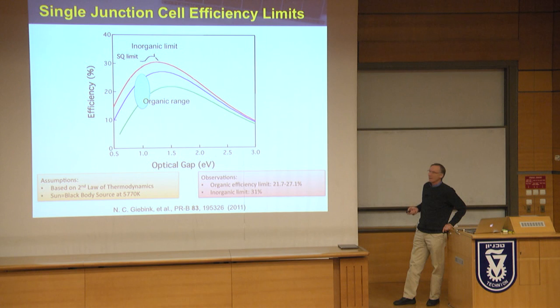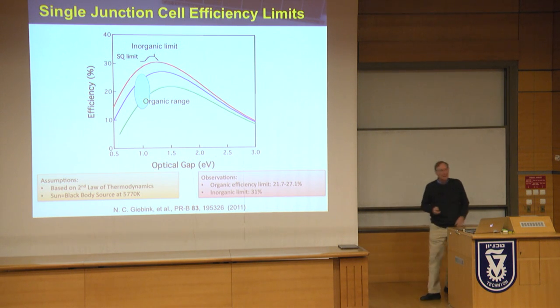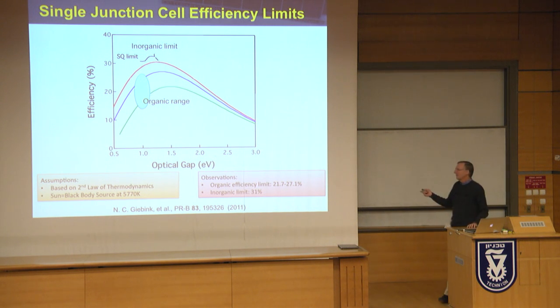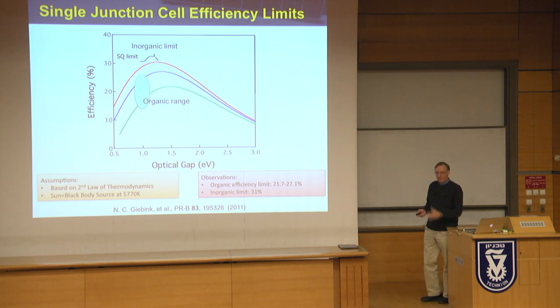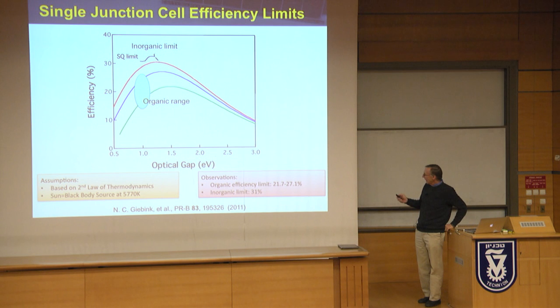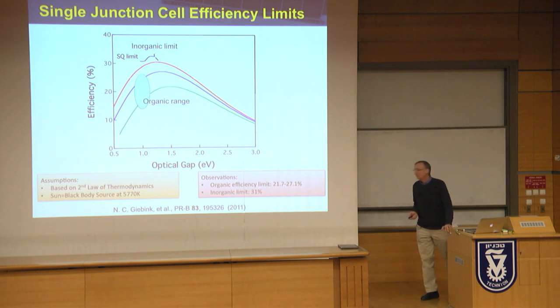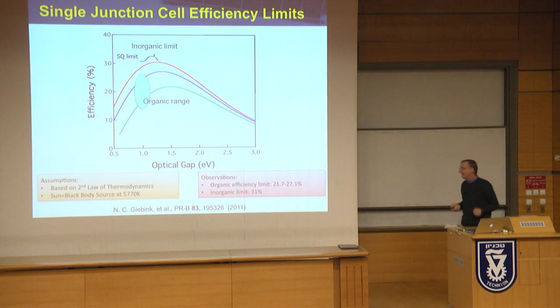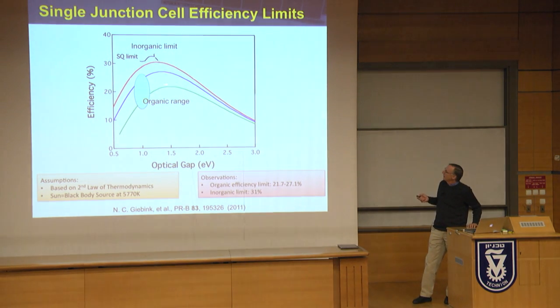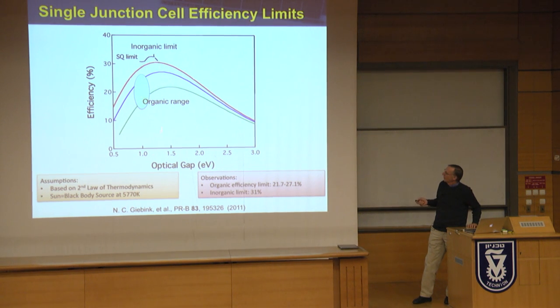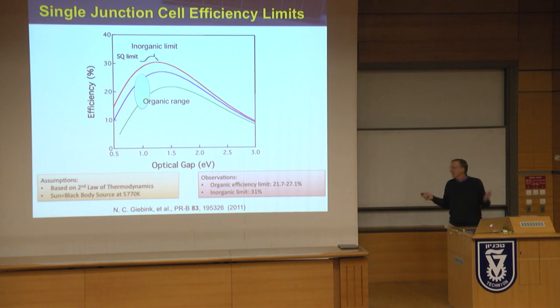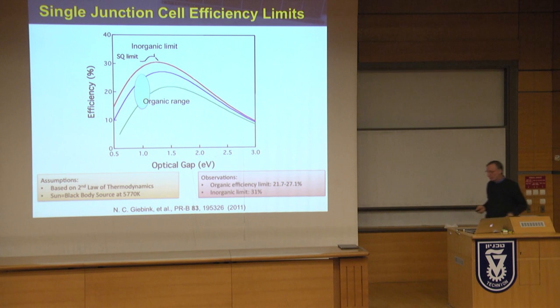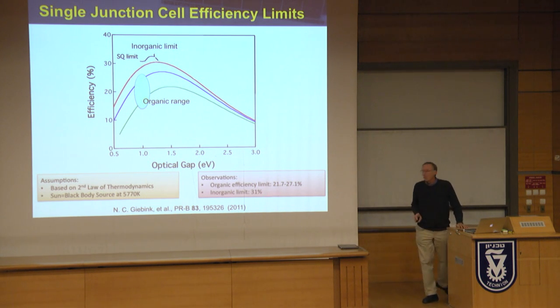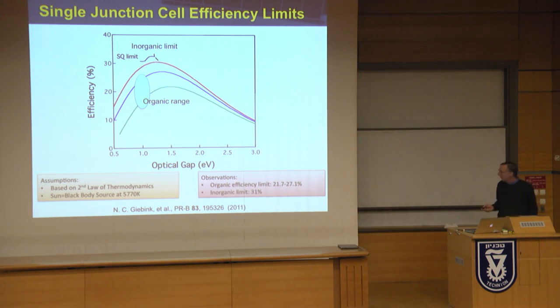And that's because you make certain assumptions, like the sun is a black body source at 5770 K, and the absorption coefficient is, well, basically you get 100% internal quantum efficiency from the band edge up, and so you can't really get to that limit. If you look at organics, because of the relaxation that occurs in the excitonic state on absorption, you get sort of a range of efficiencies here, which depends on really the dielectric properties of the organic, and I think it's safe to say that we live somewhere in there, which is again at about 1.4 eV, and it comes out to 25%. So we have a target that's actually pretty worth pursuing. It's not quite the 31%, but then again, we can go to multi-junction cells, and I'll spend a fair amount of time talking about that.